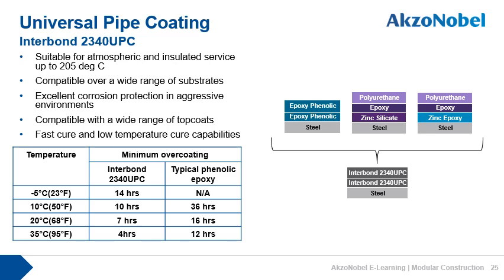Importantly, with this product, it also delivers fast cure and cold temperature cure capabilities, and that can be invaluable in modular construction projects. As you can see from the table in this slide, there is a significant time saving to be had by switching to Interbond 2340 UPC compared to a phenolic epoxy.